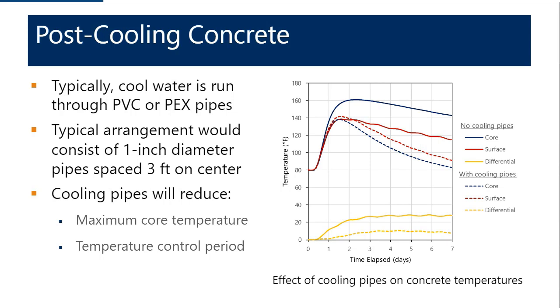And what you'll notice is there's a significant difference in the overall maximum temperature of the element. So in this particular scenario, we're reducing the maximum core temperature from around 160 to around 140. And you'll also notice that the temperature difference, as indicated in yellow, is significantly reduced, and the temperature control period, meaning the overall time that's required prior to moving forward in the construction sequence, would be reduced with the use of cooling pipes.